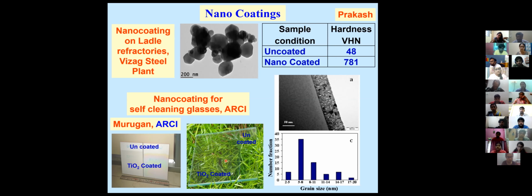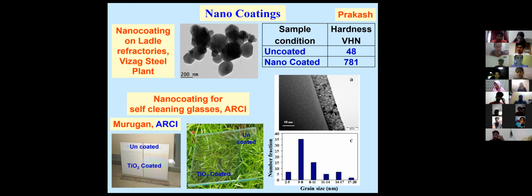This is another where I was talking about self-cleaning glasses. A glass which is coated and a glass which is uncoated. If you look at this glass here at the bottom, part of it is coated, part of it is not coated. You cannot even make out the difference at all because the coating thickness is 50 nanometers, and each nanoparticle inside that is about 10 nanometers in size. Such nanoparticles can be coated, and you cannot even make out that it is coated, and it can give you a wonderful self-cleaning property. A lot of people are excited. This is a project that we did with a lab called ARCI in Hyderabad. Now this whole technology has been transferred to an industry, and the industry is trying to make such coatings on a large scale.